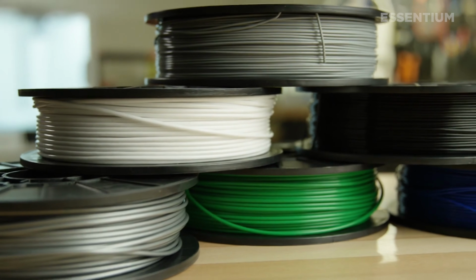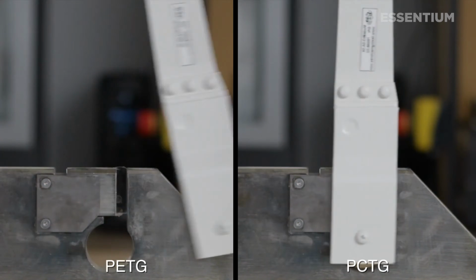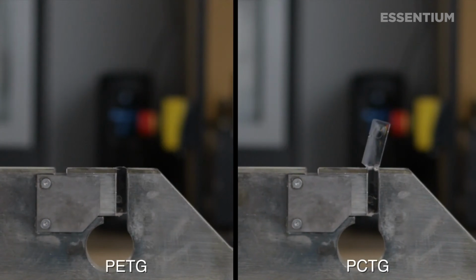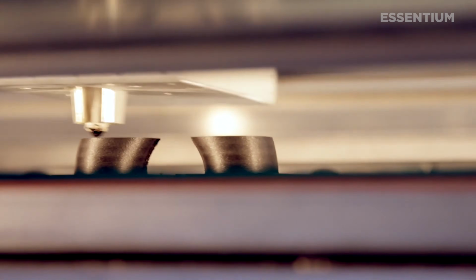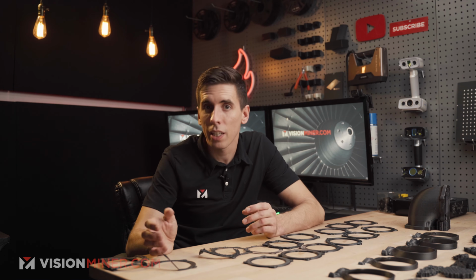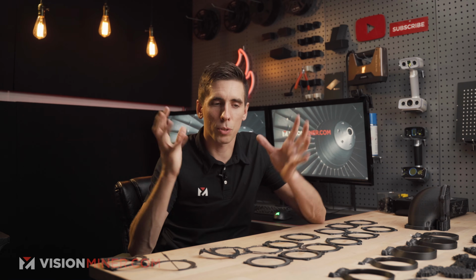PCTG, for example, prints around 240, 250 at 60 millimeters a second. Essentium, though, I believe is printing at around 800 millimeters a second, but they're printing around 300 or 400 Celsius, and it's about how long it's at that temperature, not necessarily about the temperature itself.